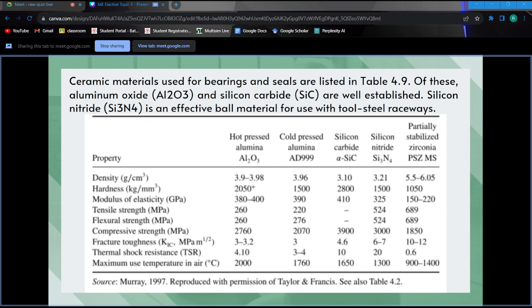Ang silicon carbide naman po ay mayroong 3.10 density gram per cubic centimeter, hardness na 2,800 kilograms per cubic millimeter, modulus elasticity at 410 gigapascals, compressive strength at 3,900 megapascals, fracture toughness at 4.6 megapascals, and thermal shock resistance at 10.